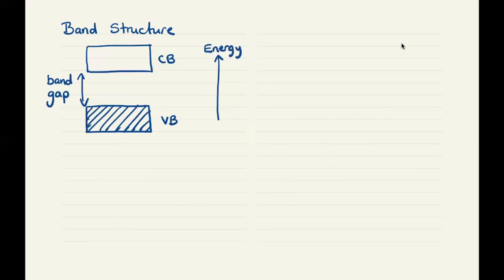The extra electron, though, which is bound to the phosphorus atom, is only rather loosely bound. It experiences the Coulomb attraction to the phosphorus ion, but this is screened by the dielectric constant of the silicon. And so its energy level is sitting just below the edge of the conduction band. And this is a small energy corresponding to pulling the electron off of the phosphorus atom and putting it into the conduction band of the silicon host.